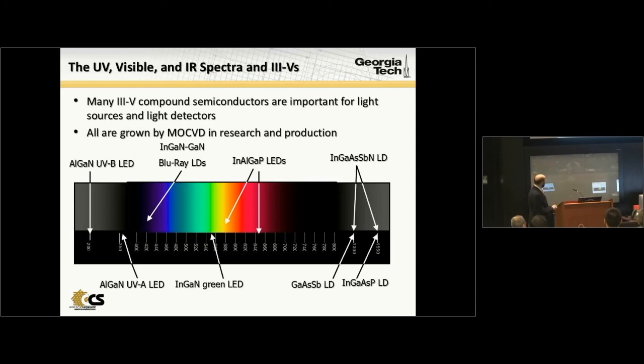This is the visible range. The red, orange, yellow that we see in our traffic signals in cars is indium aluminum gallium phosphide quaternary alloys grown by MOCVD. And the blue, green, white LEDs are all indium gallium nitride or indium aluminum gallium nitride quaternary LEDs grown by MOCVD.